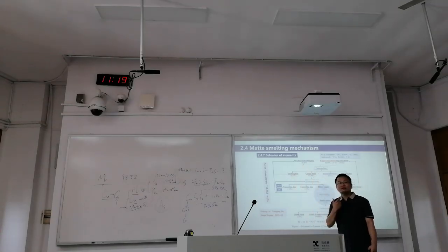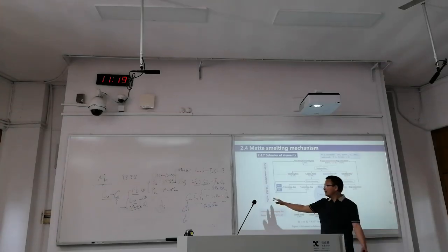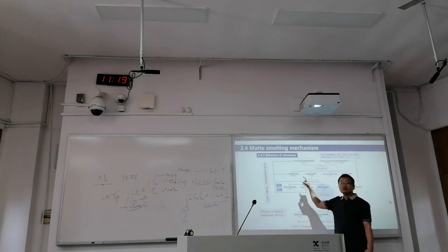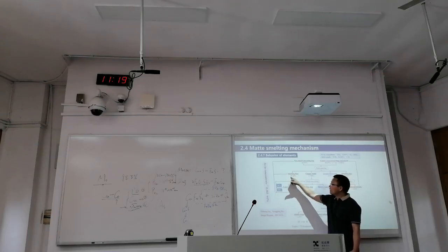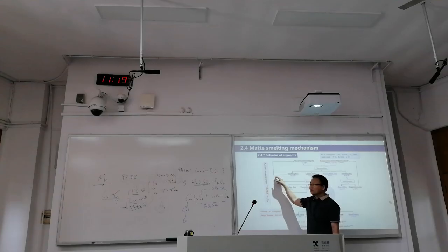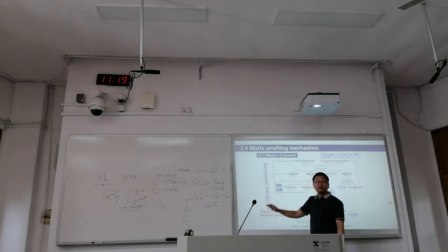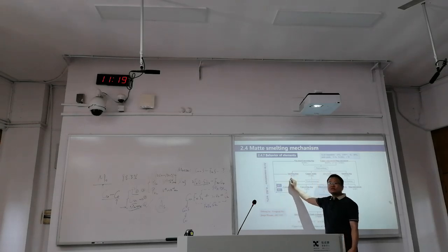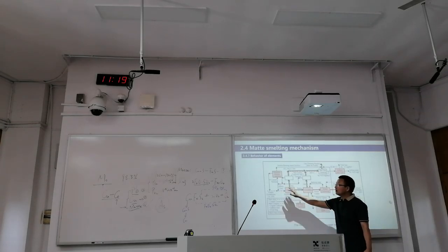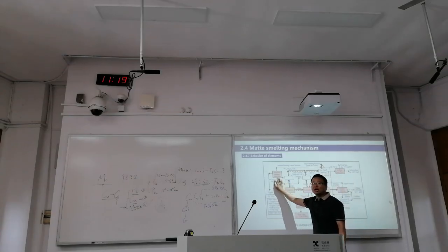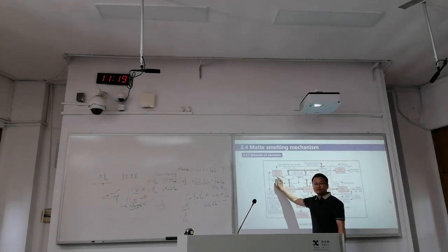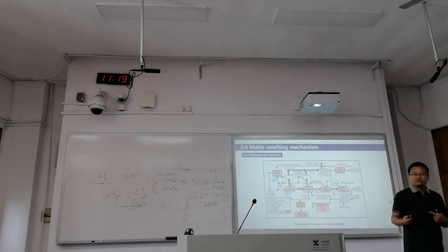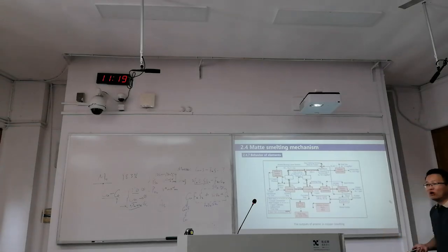You got the idea? If we have higher arsenic content, arsenic should not be circulated so suddenly. You should reduce the values, especially here. You are not returning all the arsenic back. You can return part of it, but not all of that. So this is why I am recommending that all copper smelters should have a dust leaching unit, to try to remove their arsenic. And this will help the balance of arsenic.